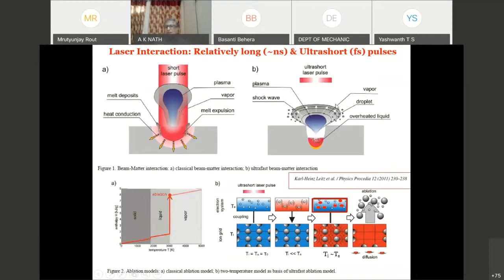But with a very short duration pulse, what happens is the electron system gets heated up in that duration, and slowly, over tens of picoseconds, shares its energy with the ions and lattice, which then also get heated up. All this happens on a femtosecond time scale.